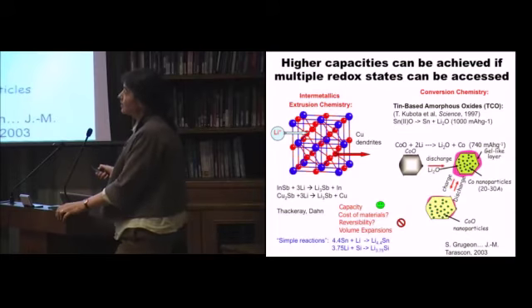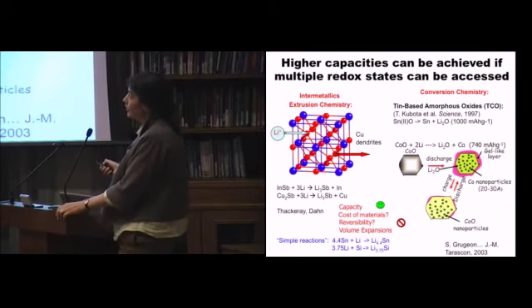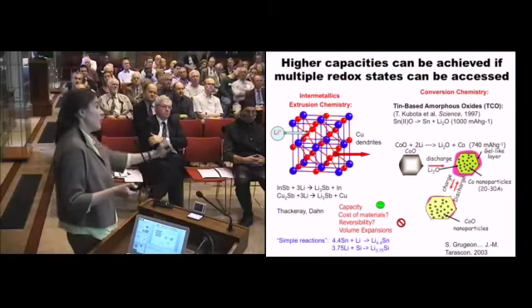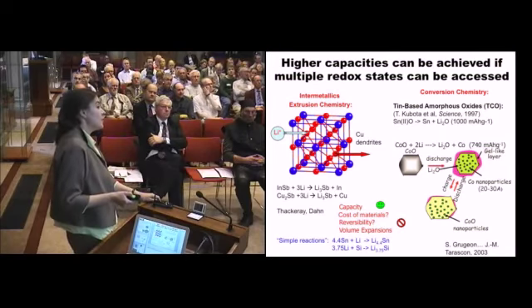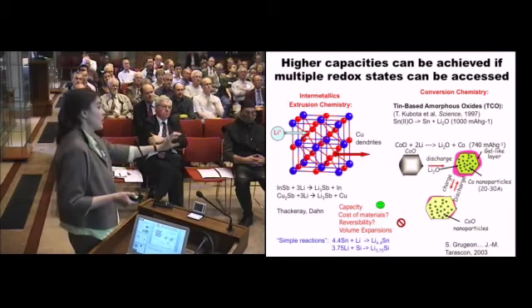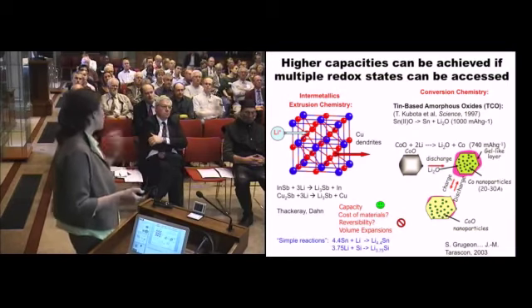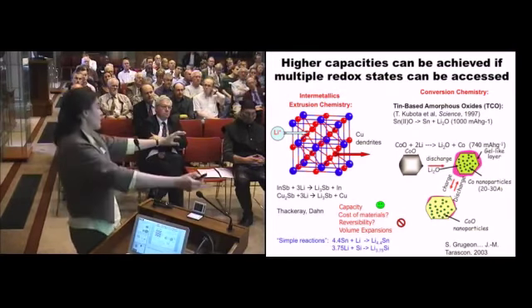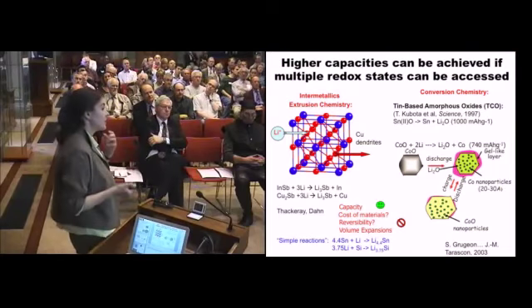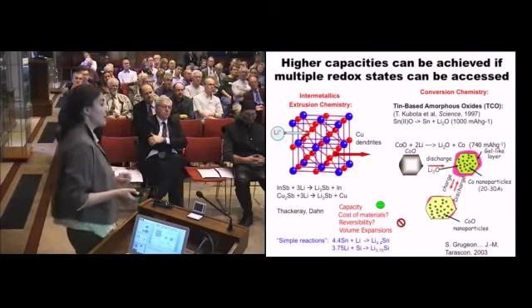There are other ways of doing it. You might, for example, insert lithium into a material and extrude or push out something else. So you can put lithium into copper antimonide and extrude a copper dendrite. But again, you've got this challenge of reversibility. If you're making a copper dendrite, you've got to then get the copper back into your material.